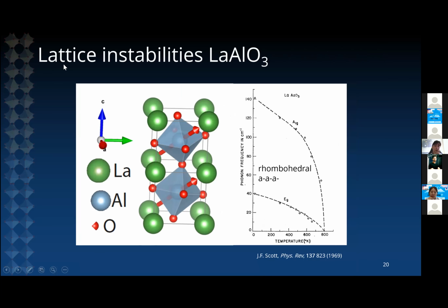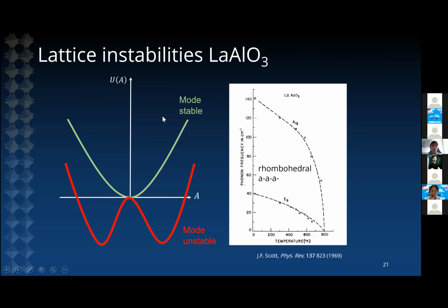So I'm going to show the example of lanthanum aluminate, which is an insulating crystal that is often used as a substrate in oxide electronics. So lanthanum aluminate has a transition from a high temperature cubic phase to a low temperature rhombohedral phase, which is in the Glazer notation a minus pattern of octahedral rotation. So associated with the rhombohedral phase, there's the condensation of two modes, an A1g and an Eg mode at 800 Kelvin. So at room temperature, this crystal is already characterized by a large lattice anharmonicity associated with this mode instability.